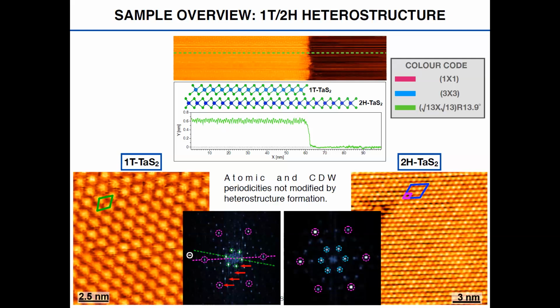We have studied the atomic periodicity and the periodicity of the charge density wave by means of fast Fourier transforms. So we are able to obtain STM images with atomic resolution, and then we can fast Fourier transform them to study the periodicities. Here in purple, the atomic periodicity of the 2H, in blue, the spots of the 3x3 charge density wave, and here the same thing for the 1T, where the spots of the 1T charge density wave make an angle of more or less 14 degrees with the atomic lattice spots.